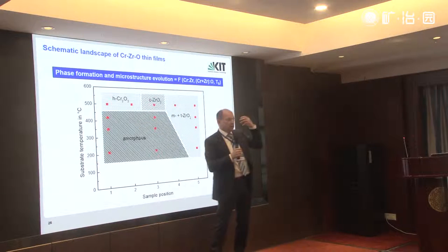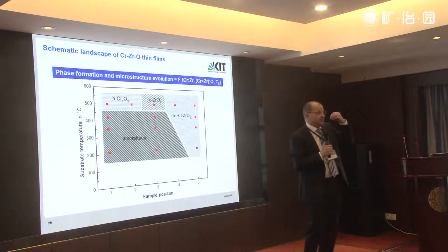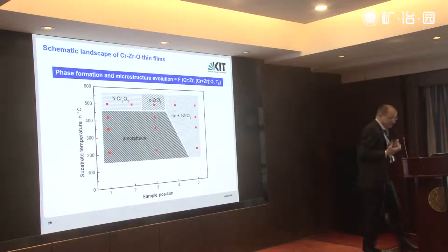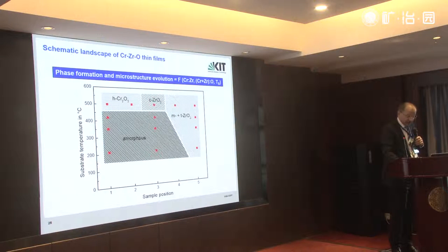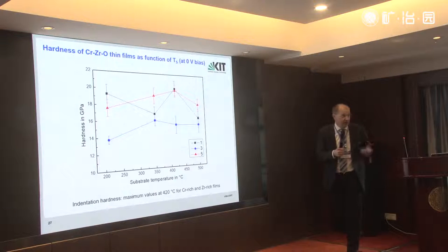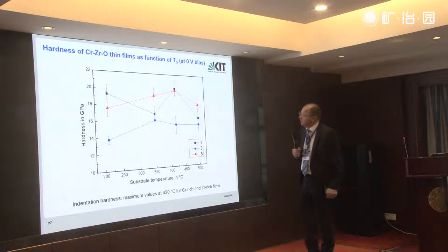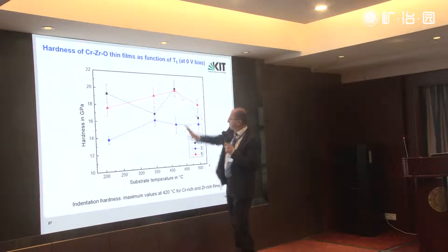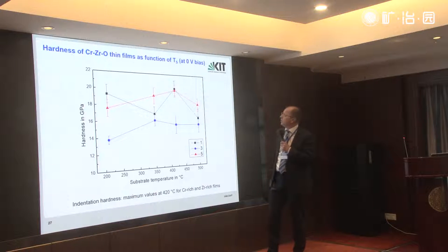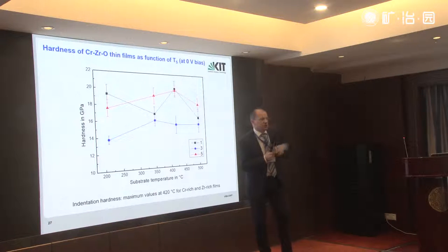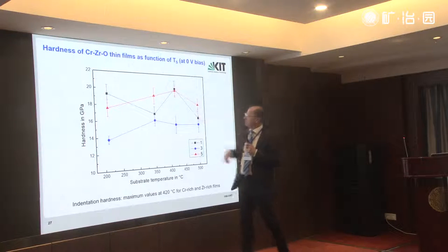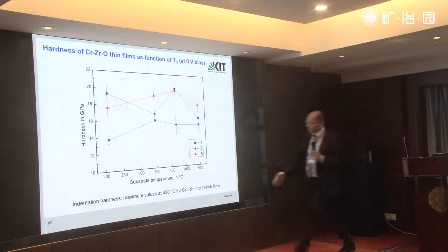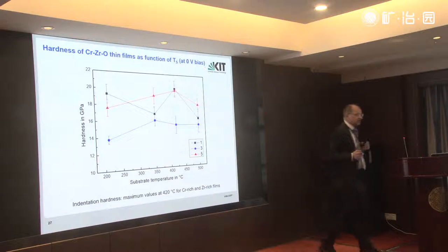So this is a landscape, so to say, giving the direction for industrial production as well, showing which type of coating you receive with different manufacturing conditions. And just a final slide here showing you the hardness of the material. We did indentation hardness investigations in gigapascal, and you can see quite promising results. The work is going on, and we are still changing some parameters to improve, but we found the highest value of about 20 gigapascal of hardness for these coatings,